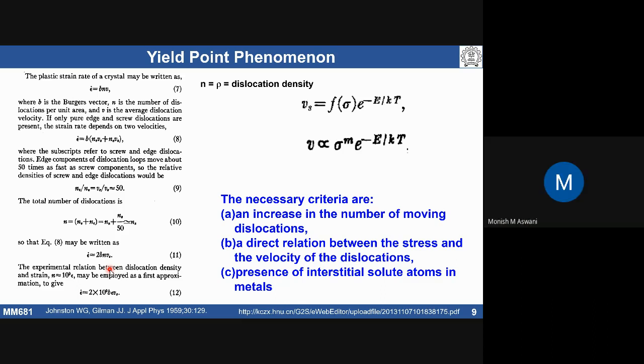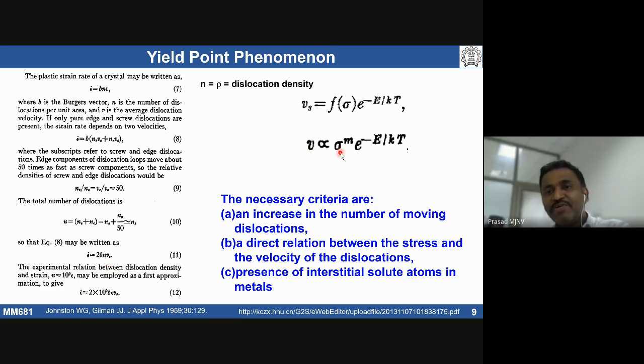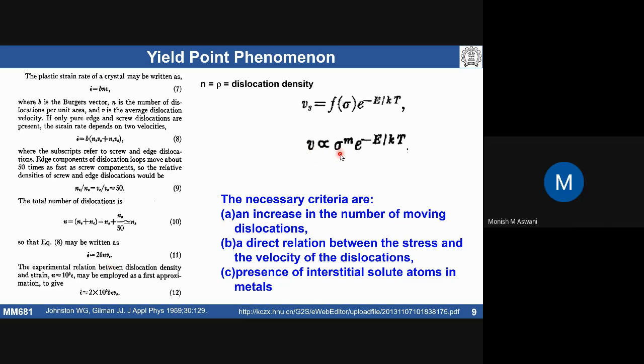So basically, the internal strain rate is going to saturate in some time with the increase of stress and thereby the increase in velocity. When that happens, to maintain a balance between the internal and external strain rate, the velocity is going to come down, and with that, the stress is going to come down, and you see the drop in that curve. Once velocity comes down, your stress also comes down.